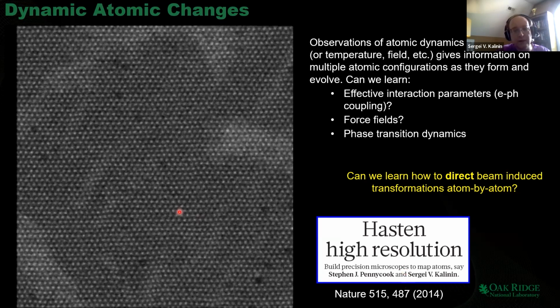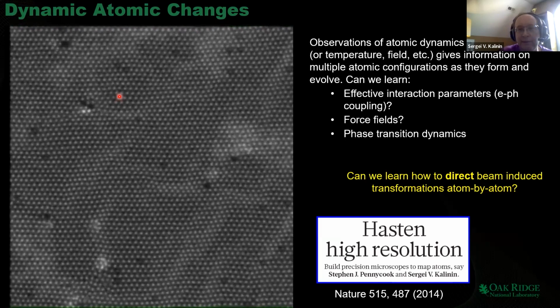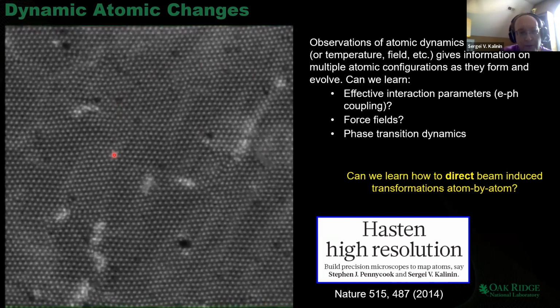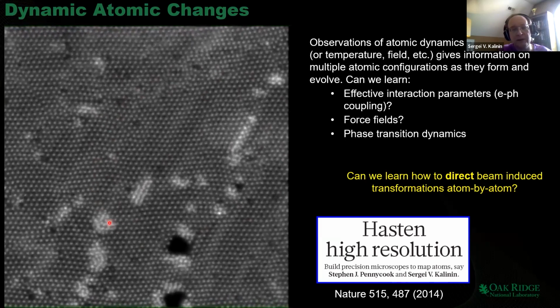So this is what really happens when you put a sample under the electron microscope. What you see here is molybdenum sulfide. So the bright dots are either molybdenum atom or 2 sulfur atoms. You can see a number of darker dots. This happens when you have 1 sulfur atom missing. So this is just 1 sulfur. Now look what happens if this material is kept under the electron beam. All of a sudden, it doesn't want to remain the same.